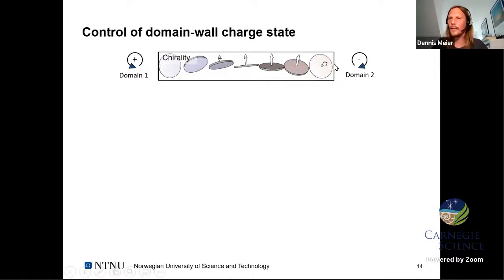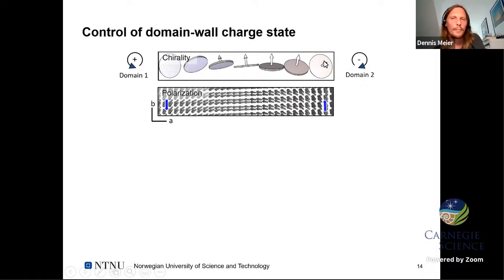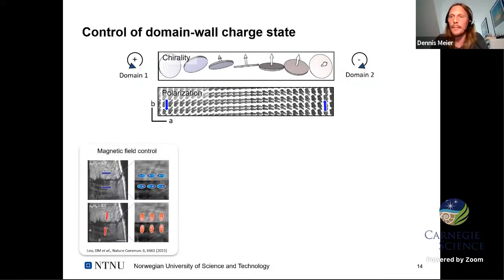But it's not just the magnetic chirality, the polarization has to follow. And there you already see we get a very interesting polarization structure at the domain walls. Even though this is a neutral domain wall, polarization up and down, side by side, it follows the rotation of the magnetic chirality. We get longitudinal Néel components and then charged domain walls in these materials. That is very unusual because this way the system has to do something about the electrostatic divergence, but it leads, as I said, to many functional properties you don't find elsewhere.